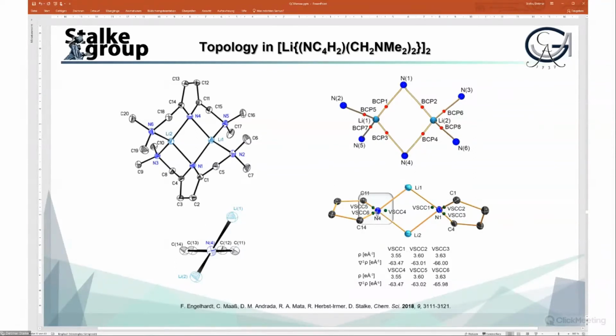So this would be lithium-1 to N1. If we look at N4, then the 2 lithiums are well above and underneath the plane of the 5-membered ring, and that would mean we have a different scenario. Is this the scenario we're looking for, for the stereoselectivity, the sp3 hybridization of the nitrogens? No, because we are lacking the 2 VSCCs towards the lithium. There is only the 1 over here.